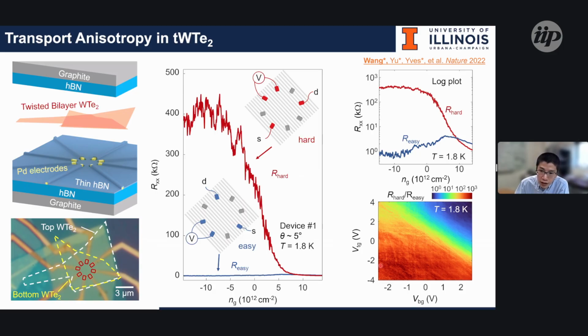If you tune the density along the charge neutrality towards the hole doping side, we see huge anisotropy. But if you tune the density towards the electron doping side, we barely see any anisotropy. So it's a kind of tunable anisotropy in such a system.